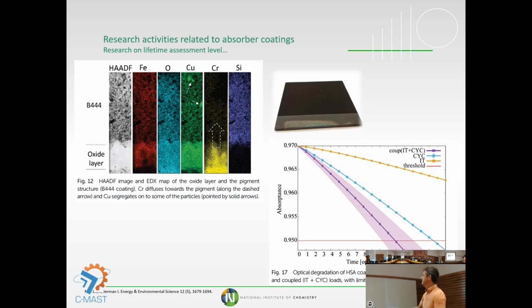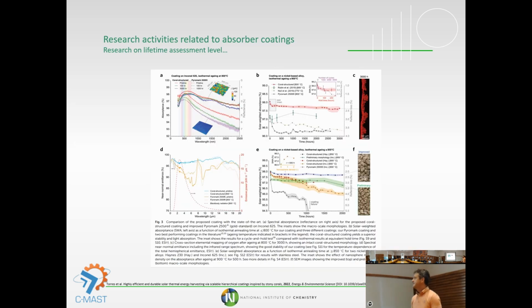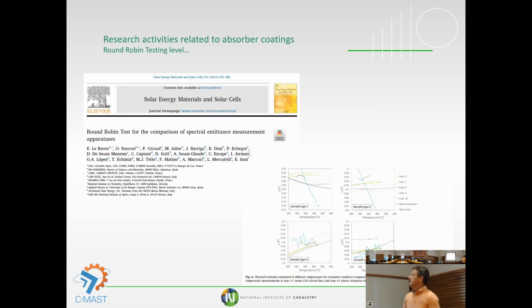in the first 12 years. So then they decide if the coating should be maintained or replaced, or everything stays like this. Other labs also try to do the same research with different coatings. As I said, benchmarking is quite often also an issue. We often do the round-robin test, where different labs try to do the same in order to prove that, let's say, our evaluation was good, was correct, and so on.